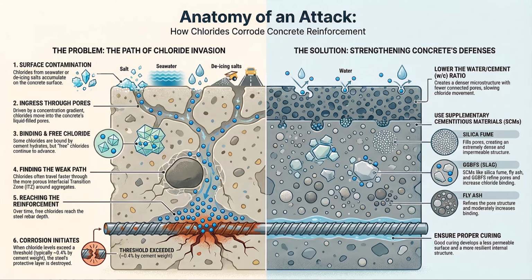And what happens when we introduce these high-performance SCM blends? The difference is just striking. GGBFS mixes at 50 to 60% replacement cut that penetration depth almost in half. They bring it down to 10 to 20 millimeters in 10 years. The chloride front is moving much, much slower. So the concrete cover has years, even decades, more time to do its job. Exactly. And when you incorporate silica fume, those penetration depths drop even further, down to the range of 5 to 15 millimeters after 10 years.